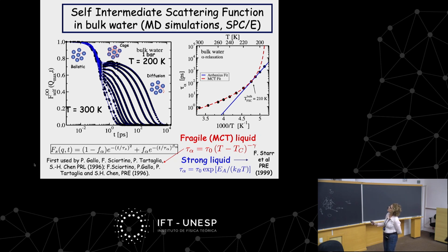That is, at the beginning, the relaxation time of the cage behaves according to mode coupling. And then here it changes trend and is due to hopping. It's still a relaxation time, but it's due to hopping phenomena. So we can see also the difference between these two phenomena.